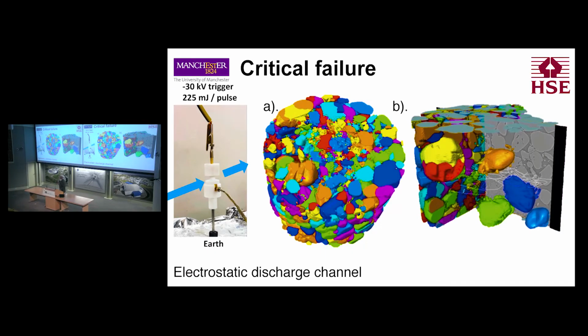We can create a spark down the center of one. We can create a very localized, short-lived, high-intensity pulse. In some explosive, that's enough to set this material off completely. In others, it controls a channel down the center of it that allows us to work out how the material's responding to this defect within the explosive. And you can see that it's rubblized the material down the discharge path, but it's also taken some of that material, vaporized it, and of course chemical reactions occurred as well.